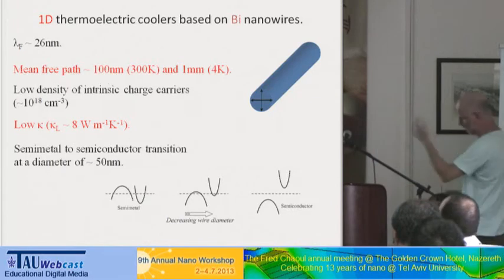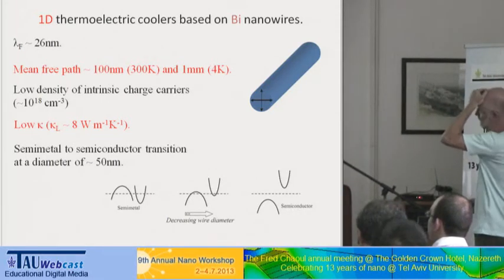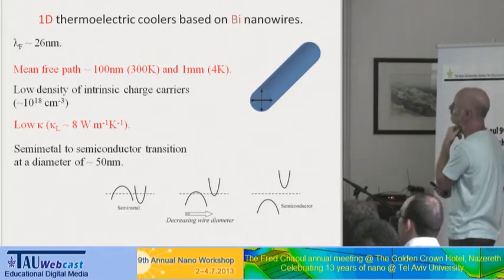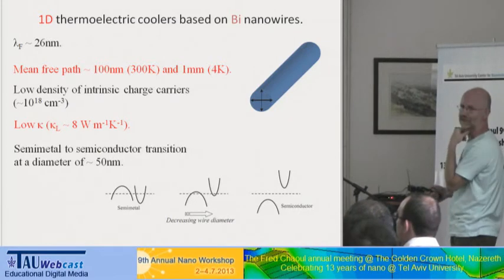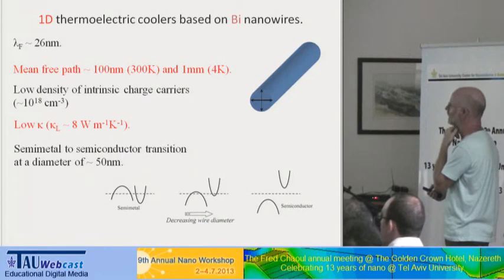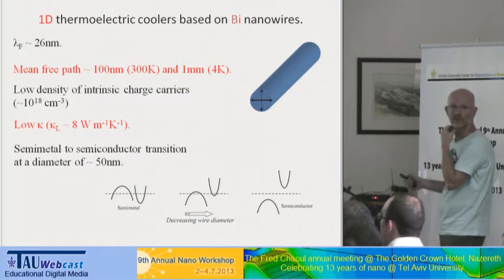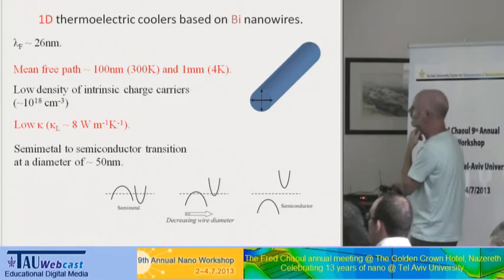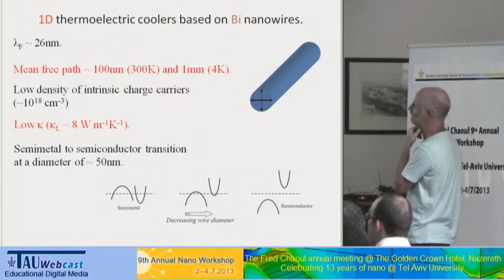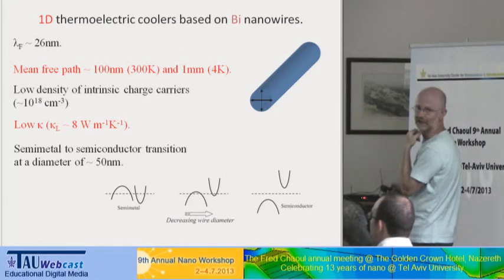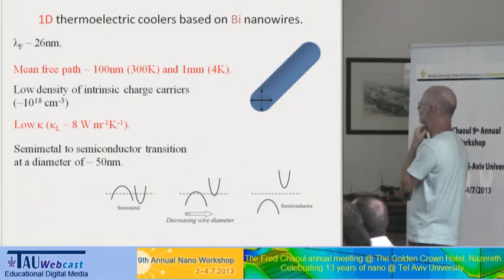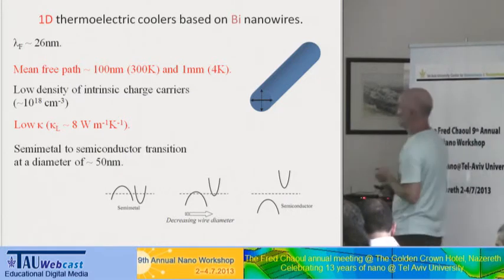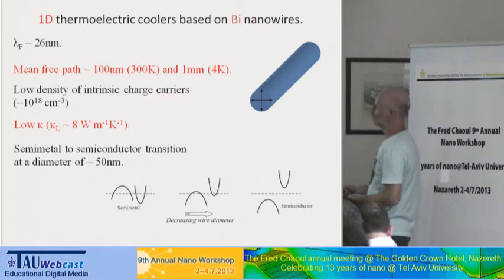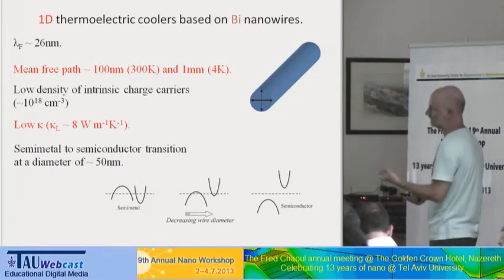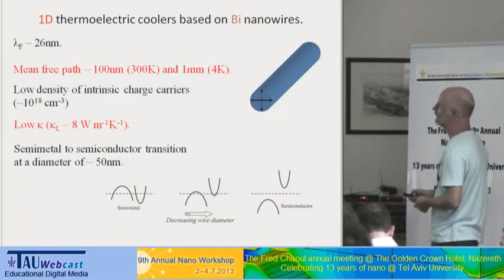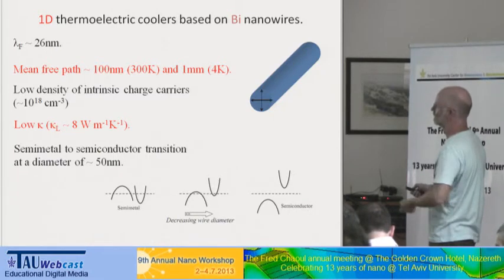All right. Now we thought that if we want to work with one-dimensional materials, why not work with bismuth? Bismuth has very interesting properties. First of all, the Fermi wavelength of bismuth is 26 nanometers. It means that once we make nanowires of bismuth with a diameter that is less than 26 nanometers, we have a one-dimensional conductor. And it's easy to make wires like this, very easy. And the second thing is that the mean-free path of carriers inside bismuth is really, really long. I mean, at 4K, it is extremely long. So we expect the electrical conductivity to be extremely high if we make short wires. And also the lattice thermal conductivity of bismuth, because bismuth is a heavy atom, it's low. And so once we make nanowires, it's going to be even lower.